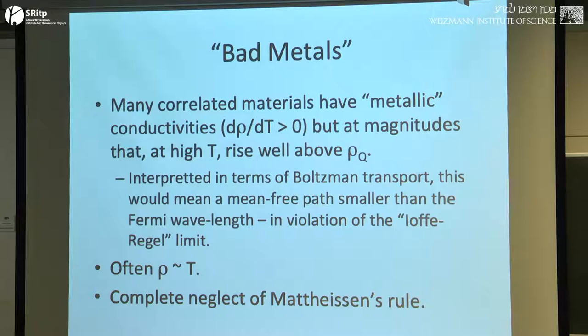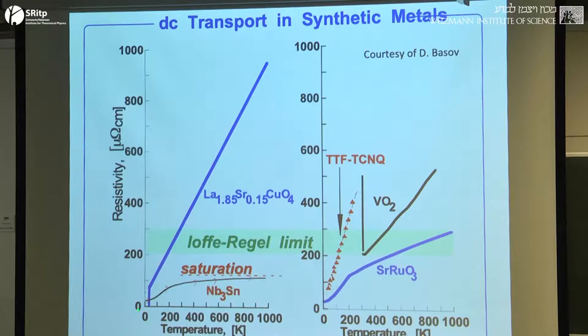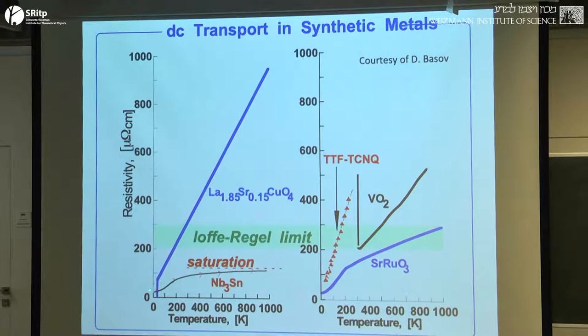Okay, so here's some examples. So here's this data in niobium tin that I showed you before. This is the A15s. If I were to show you copper on this plot, it's this black line down here at the bottom. You just can't see it on this scale. These things are much more resistive than good metals. So here's niobium tin, and here's optimally doped cuprate lanthanum strontium copper oxide. Here you can see its linear temperature dependence. This is from a slide by Dmitry Basov.